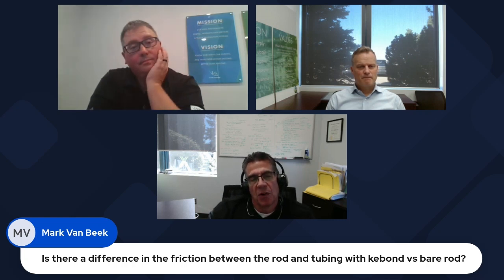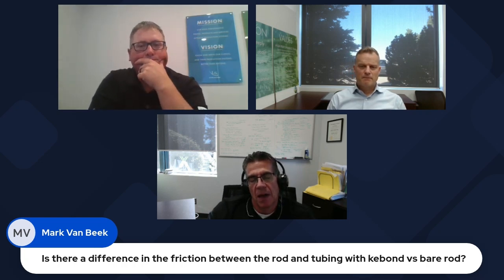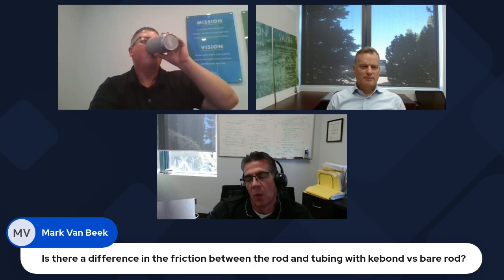We are continuing to evaluate friction using a laboratory rotary wear test equipment, and it simulates PC pumping, and it comes with a highly sensitive torque cell where we can measure the frictional resistance between the rotating rod and the tubing, and then we convert that back to a friction coefficient. And we've done comparative testing between bare and coated endless rod against both J55 and HDPE-lined tubing with a variety of contact loads and various fluids, oil, water mixtures, and solids.